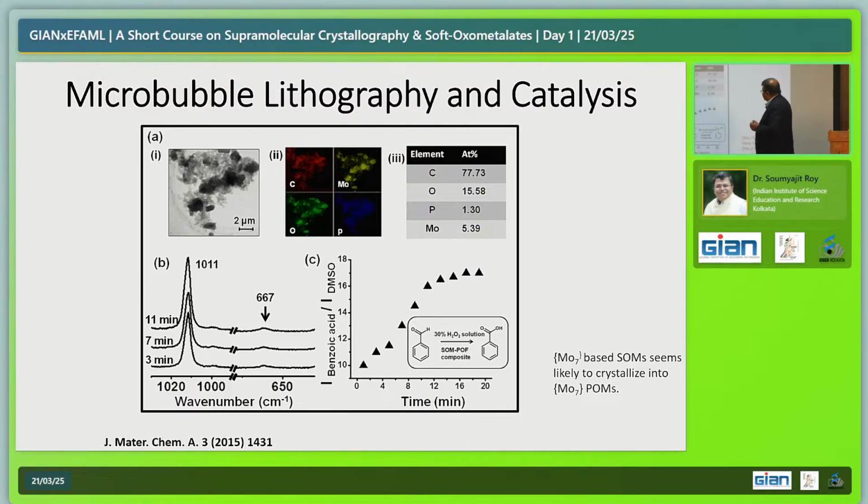Because we were studying benzaldehyde oxidation to benzoic acid, she was able to show that this peak, which was the signature for the benzoic acid, slowly increases, and it only increases on the trail. And if you go out of the trail, there is no reaction whatsoever. So that's why we called it site specific reactivity.